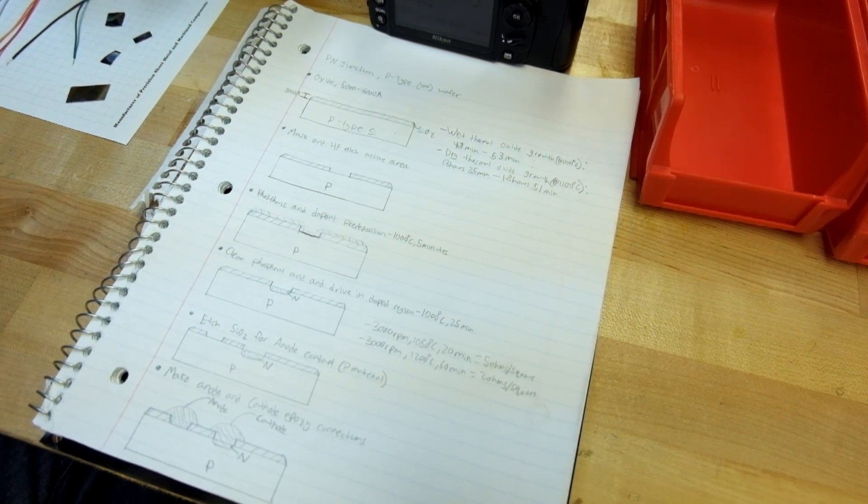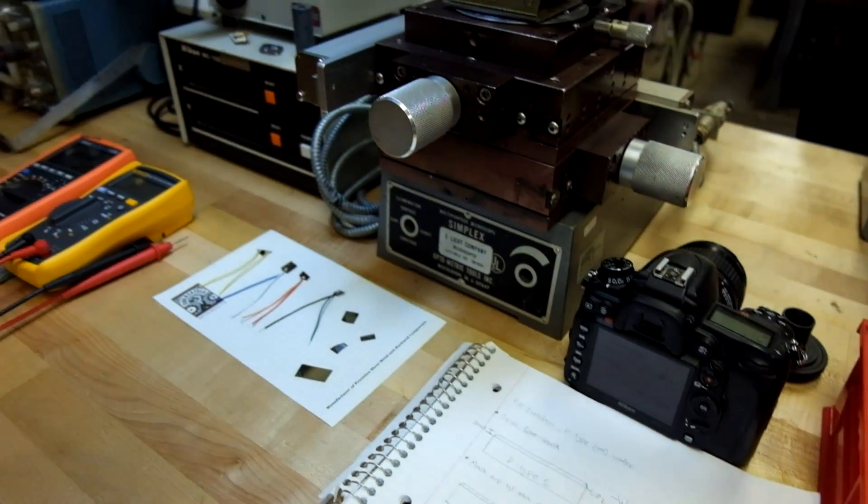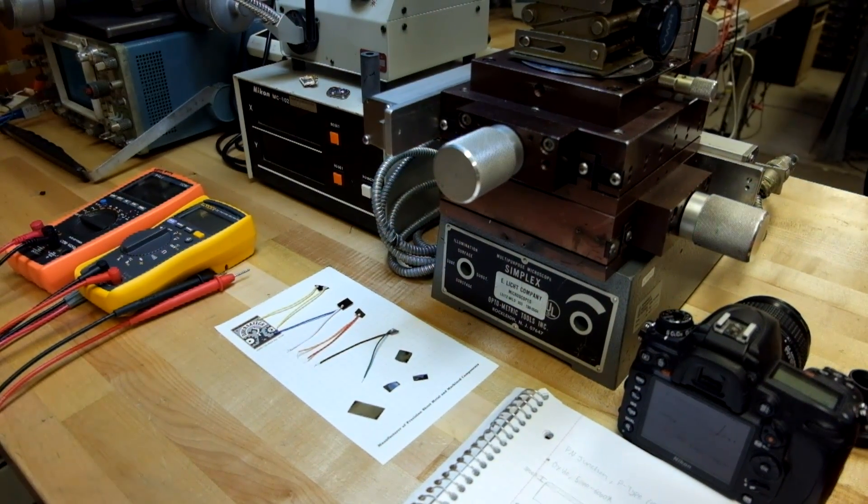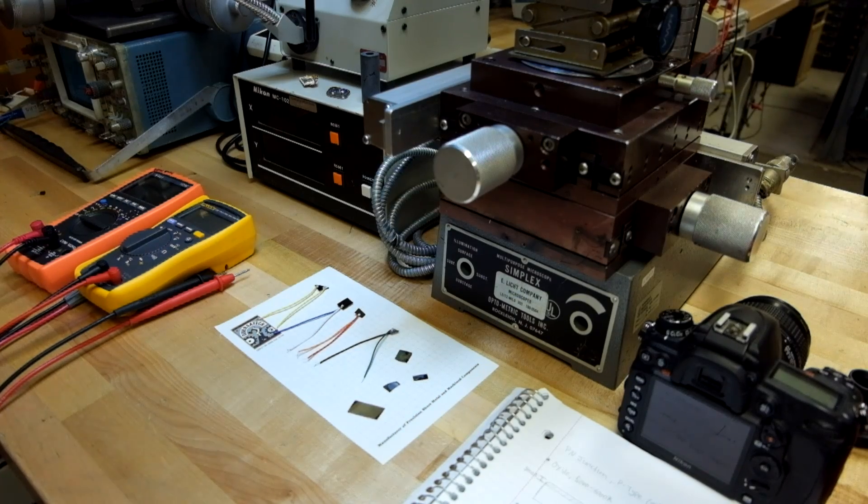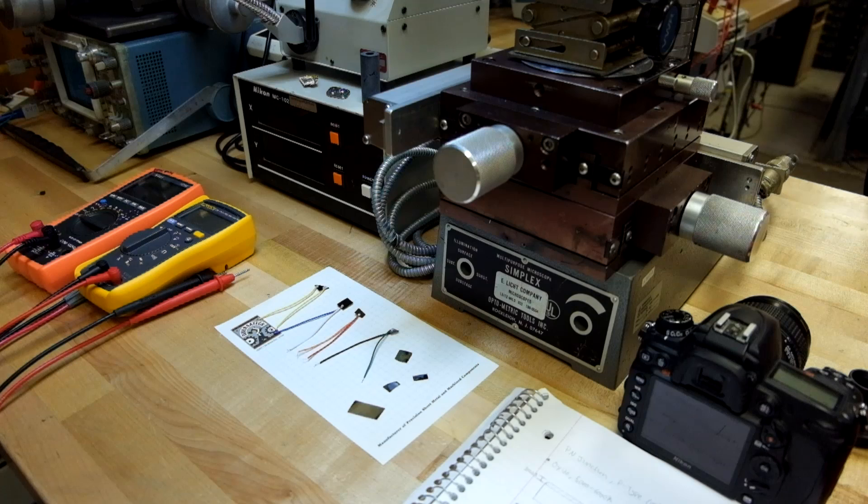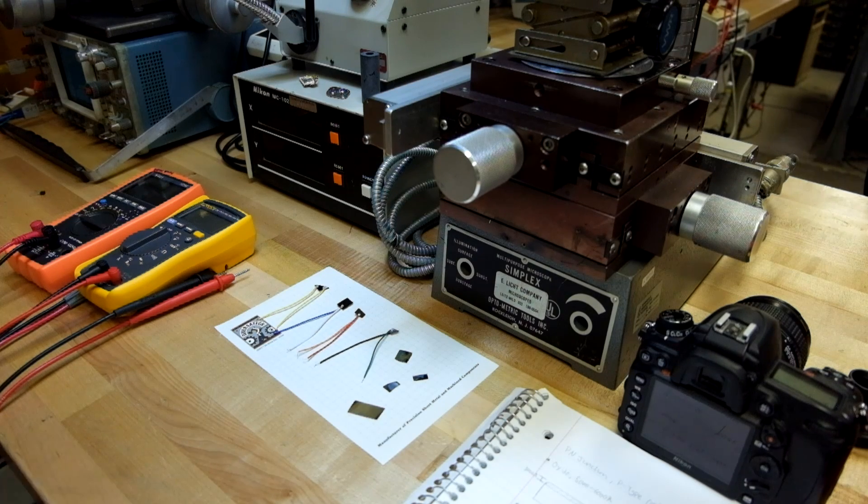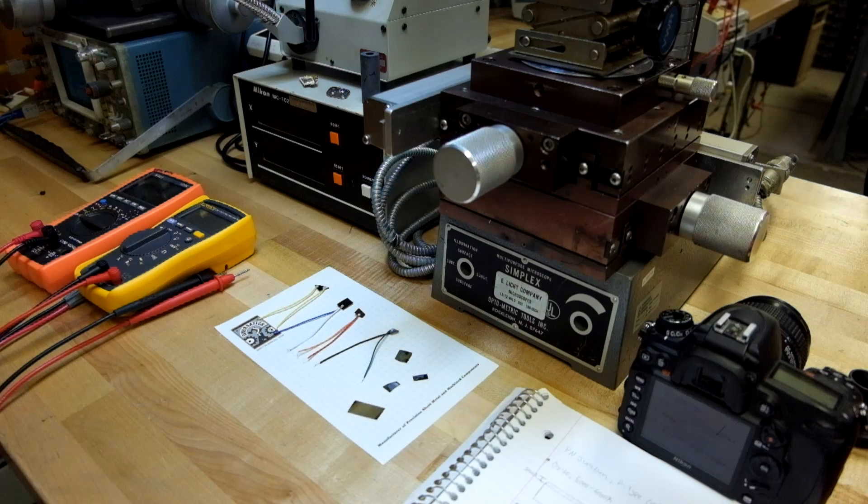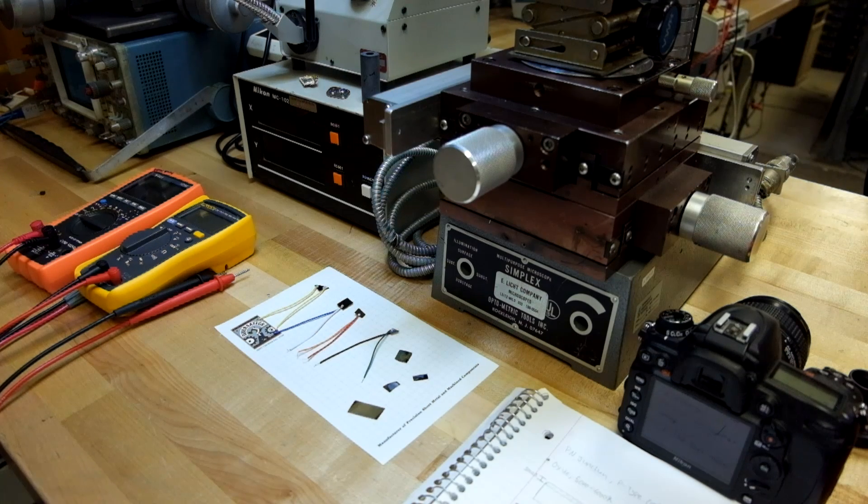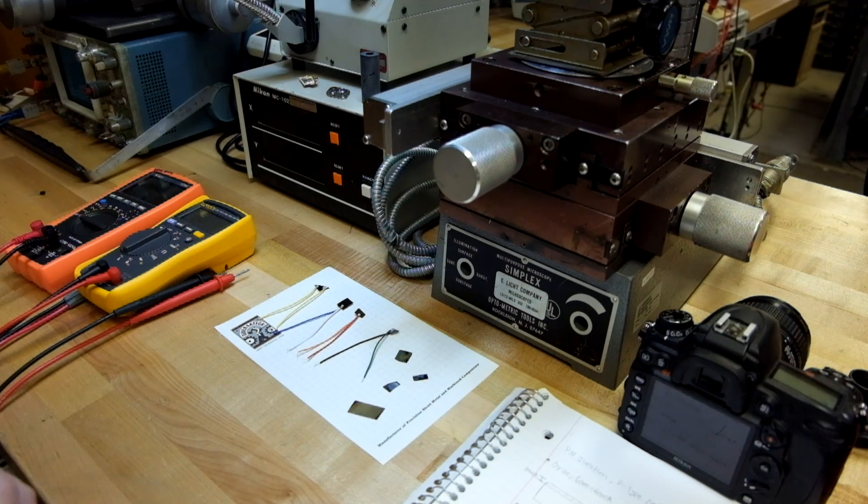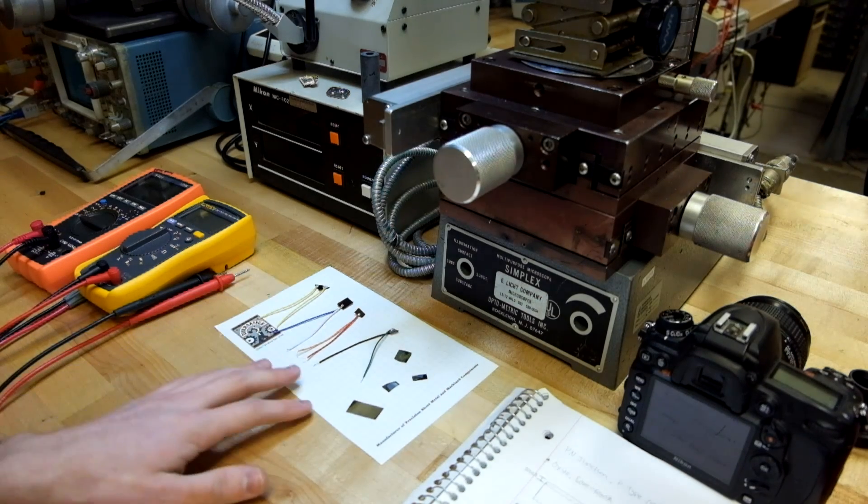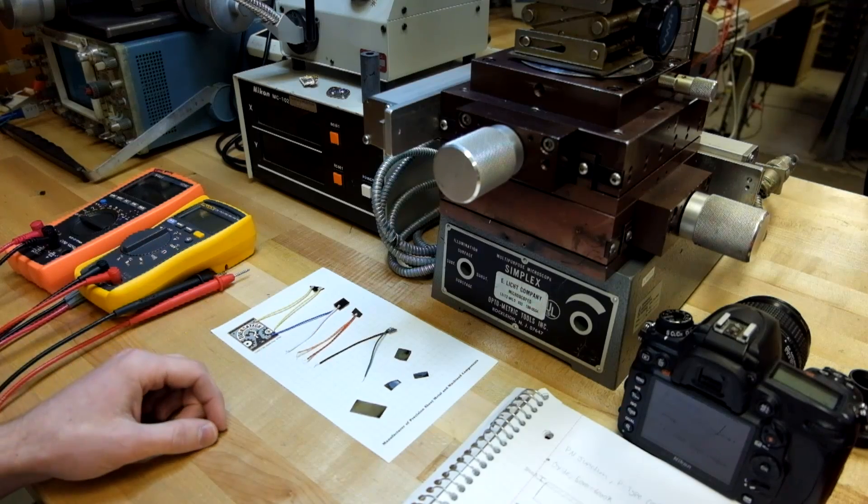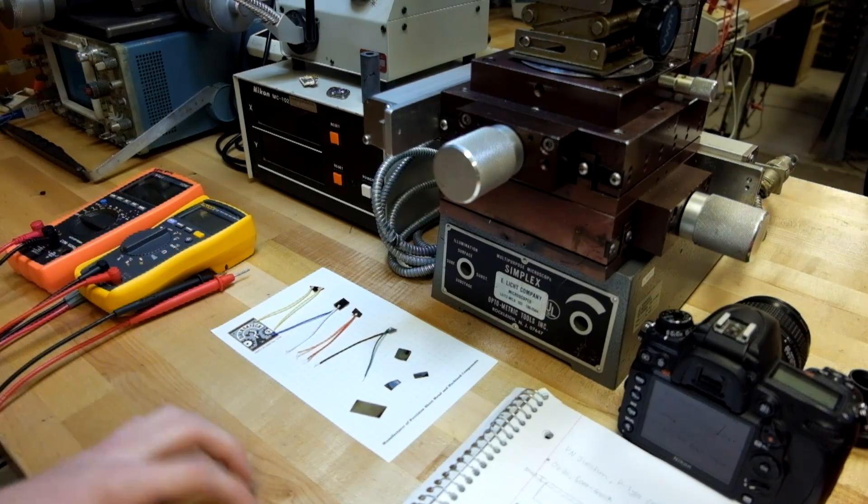The reason why I'm calling these solar cells and not diodes for the purpose of this video is because if I were to put them on a curve tracer, they wouldn't be anything near what you'd expect to see as a diode. Most of them actually work in the reverse direction because the band gaps for them are quite screwed up. For a solar cell, you want the band gap to have the highest efficiency. You want your band gap to be around one and a half electron volts, actually a little bit less than 1.5 eV. And to get there, I had to increase the dopant concentration on these quite significantly.